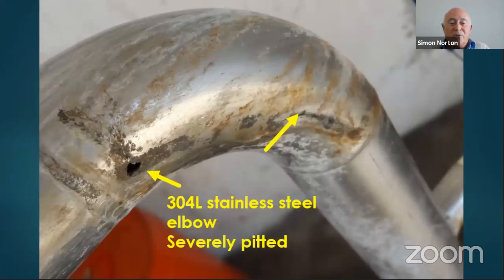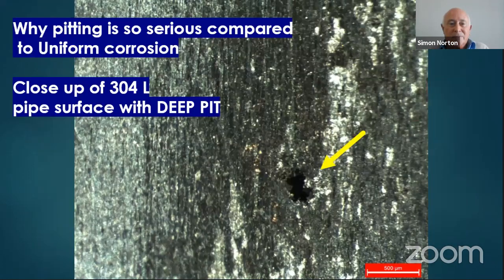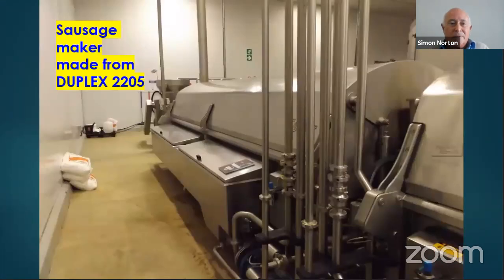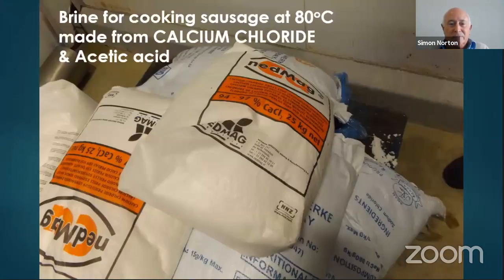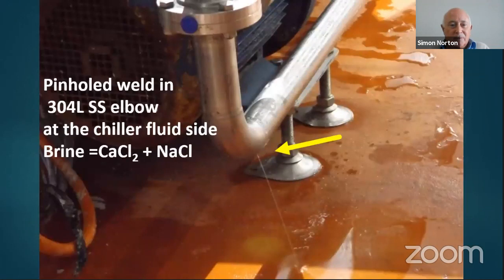This is just an example of how 304 stainless steel can severely pit and damage a plant. You can see close up what actually happens. This is the machine that was finally made with DUPLEX stainless steel. And in this particular case, this weld was a 304 weld at the same plant, 304 pipe, which should never have been there. The weld was not properly done, so of course the customer had a catastrophic failure and it had to be sorted out.